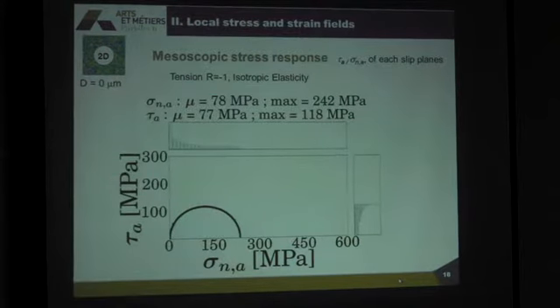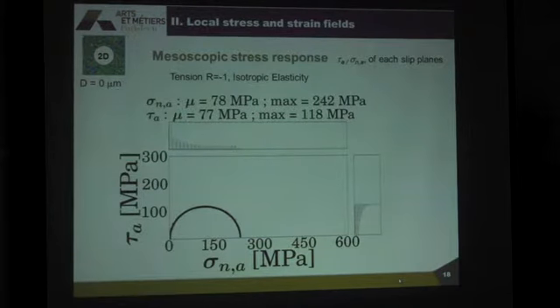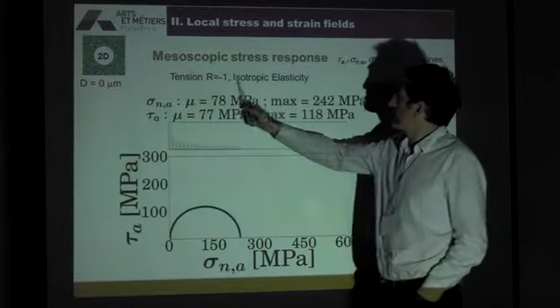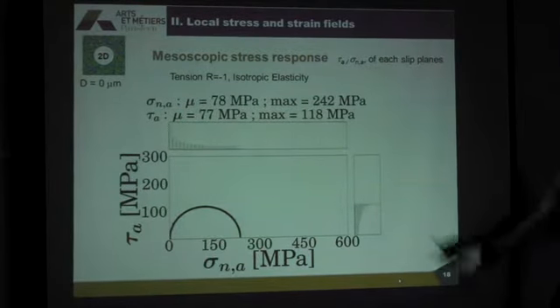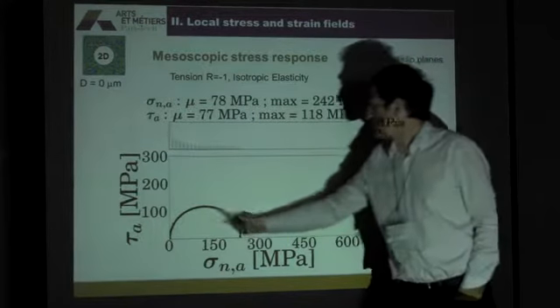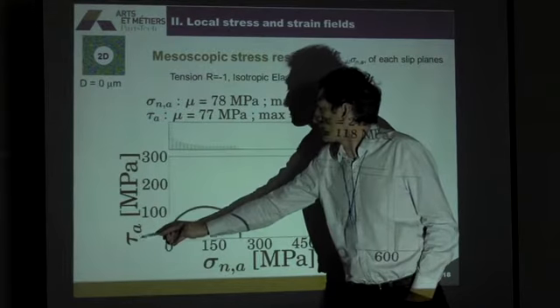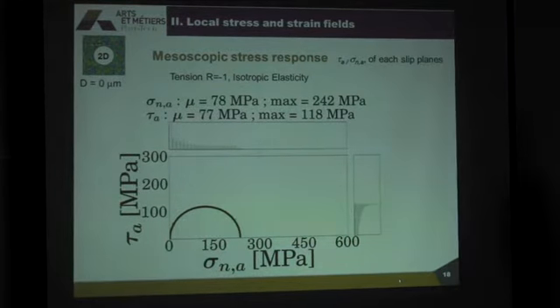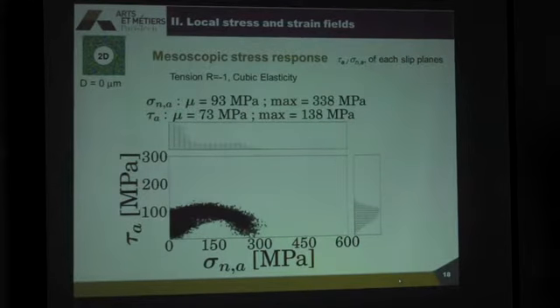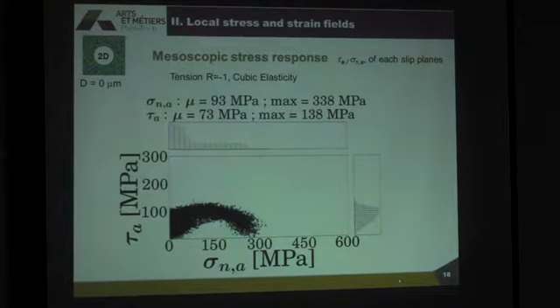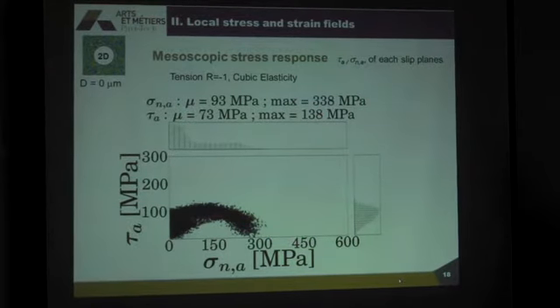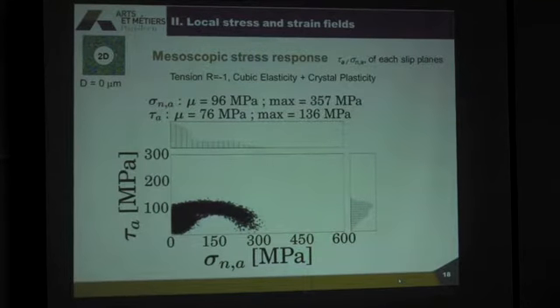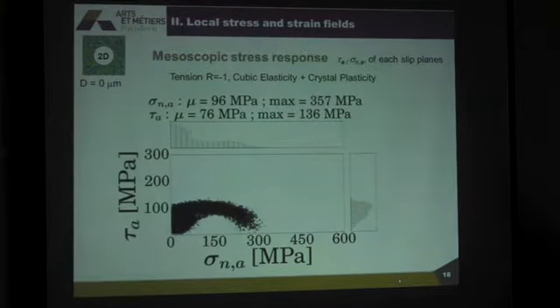Let's start with no defect. I assume an isotropic elasticity and, with no surprise, I find for this representation of the normal stress amplitude a more circular distribution. Now, what happens if instead of isotropic elasticity I use cubic elasticity? You get a strong scatter of the mechanical stresses and strains. And now, if I add crystal plasticity, it's almost the same as the cubic elasticity — the differences are not that big when we have no defect.